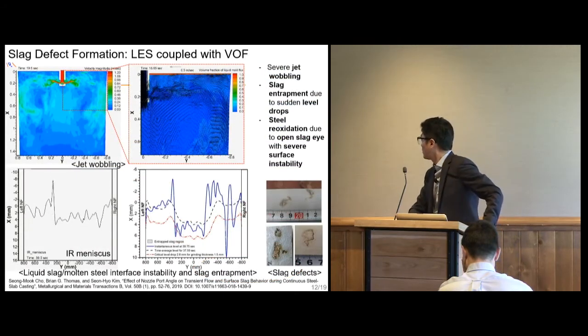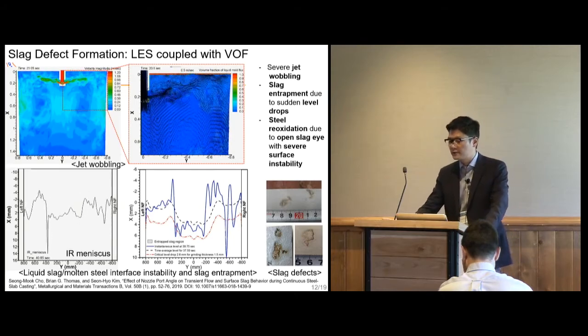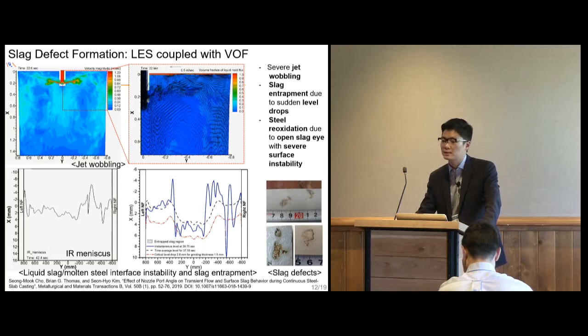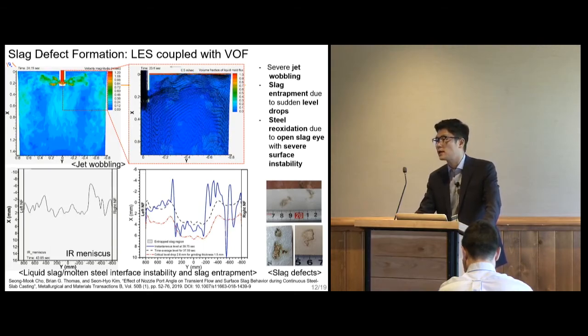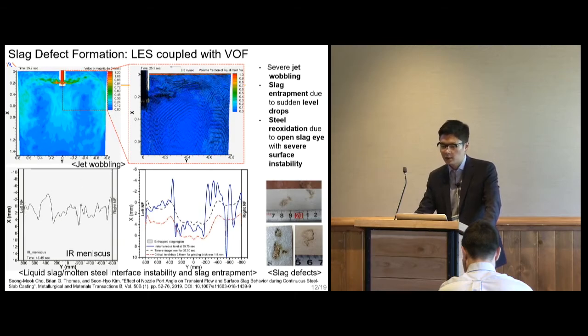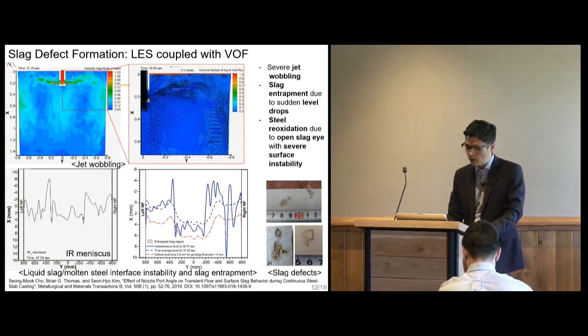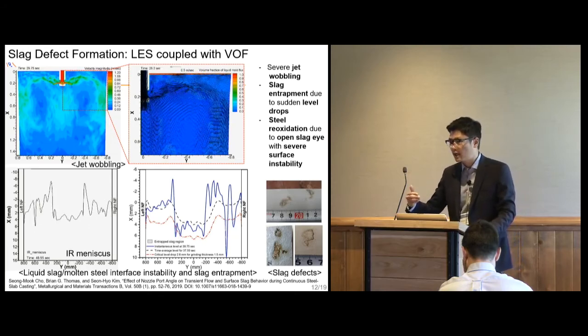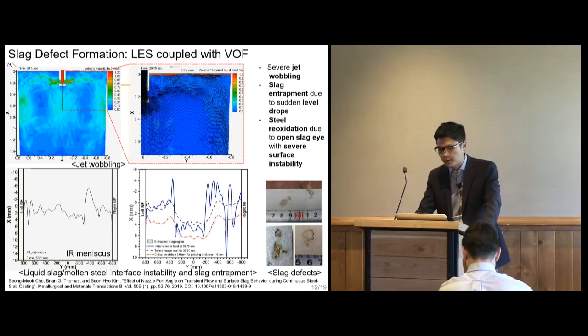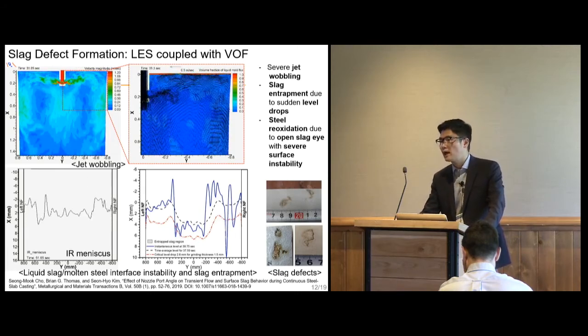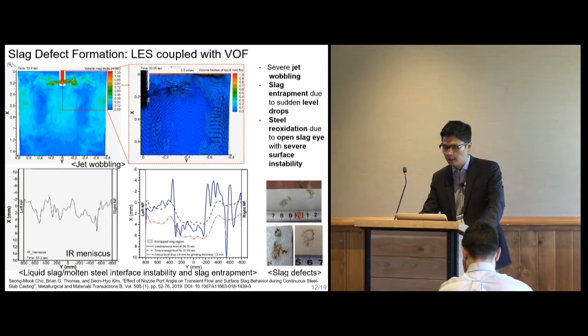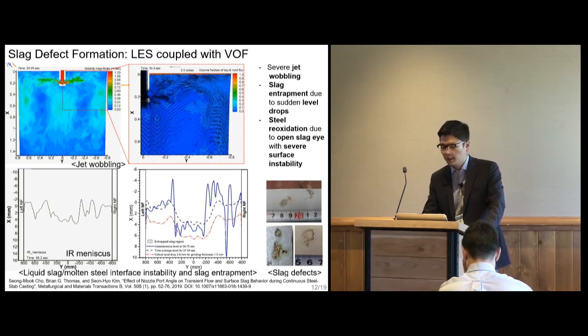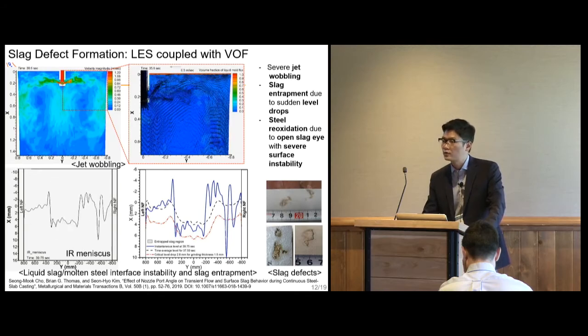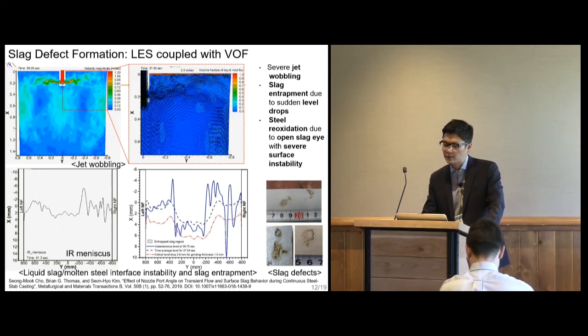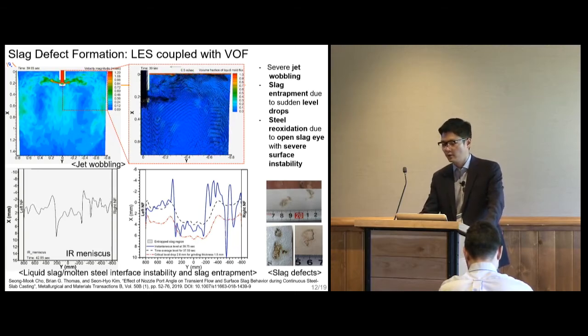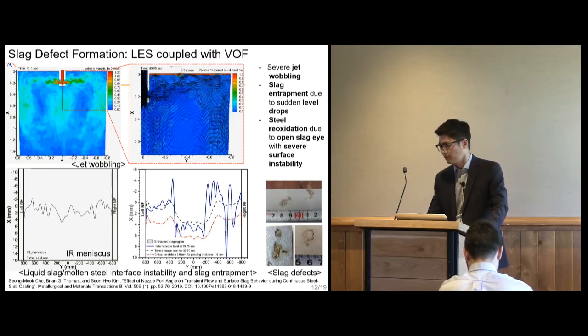This slide shows our LES coupled with the VOF simulation to quantify the transient liquid slag and the molten steel interface and slag entrainment defect formation. Jet flow from the nozzle is wobbling, showing an up and down motion in the casting direction. And this causes instability at the liquid mold flux and the molten steel interface. Sometimes this instability is so severe that the liquid mold flux is entrained by the solidifying shell, resulting in the critical defect on the final steel product as shown in the bottom right photos.